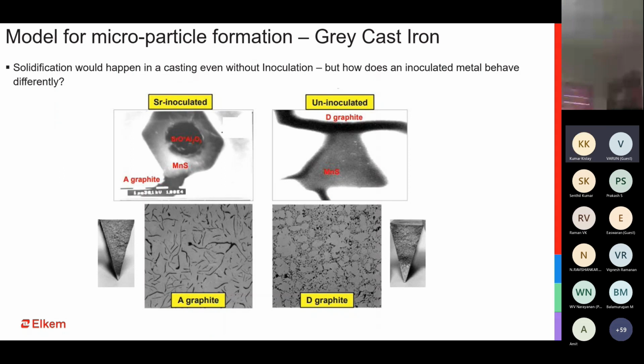So I told you about how the ferrosilicon and how the inoculating element works. So like I mentioned, solidification would happen inside a casting, inside a mold. When you pour a liquid metal, the solidification would happen even if we do not add inoculant. So it's not that if you don't add an inoculant, the solidification would not take place. Why? Because your metal will have some inherent nucleating potential, will have some inherent impurities which would act as the site for growth. So there will be solidification.